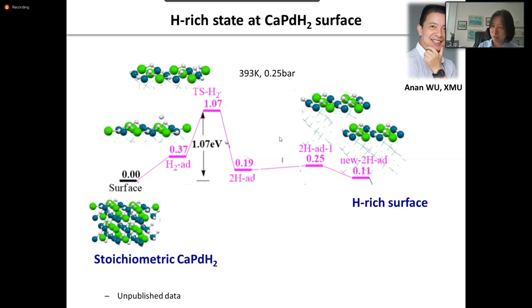As Professor Chen mentioned before in the opening remarks, we know that surface chemistry is very important for catalysis and for electrochemical reactions. And for this calcium palladium hydride, the surface hydrogen content would easily be more than that in the bulk phase. Although we haven't continued hydrogenation to an even more hydrogen-rich surface, if you compare the energy state of the starting state to the final state, there is no significant difference in the energy state. Note that we run this at 120 degrees Celsius and low hydrogen pressure. So if you apply high pressure, the driving force will be even stronger.